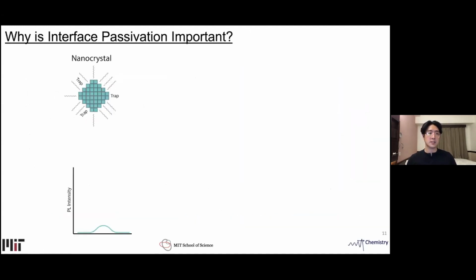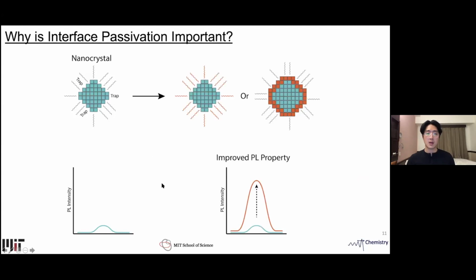So what is interface passivation and why is it important? For a colloidal semiconductor, such as quantum dots or nanocrystals, if we have an exposed surface, it can act as a recombination center that results in poor photoluminescence efficiency. However, by introducing a proper ligand system or an inorganic shell, we often see an improvement in the photoluminescence property, and that is due to passivation of these trap states.